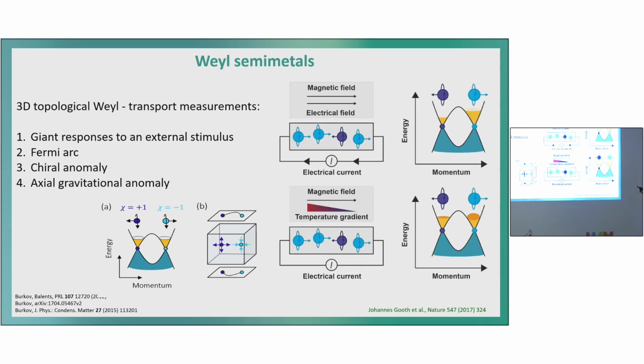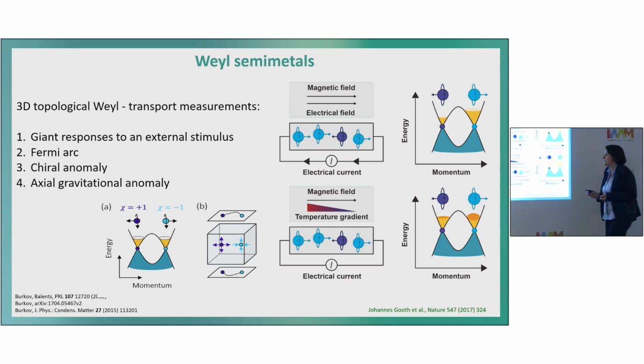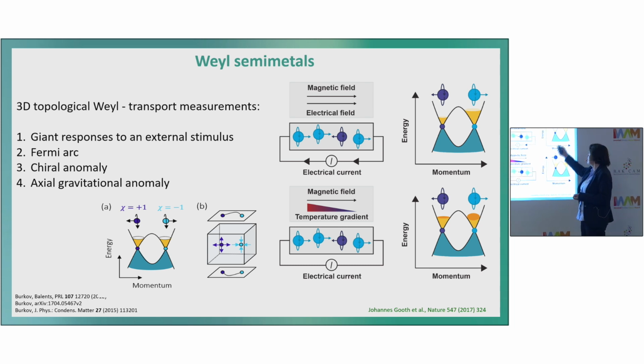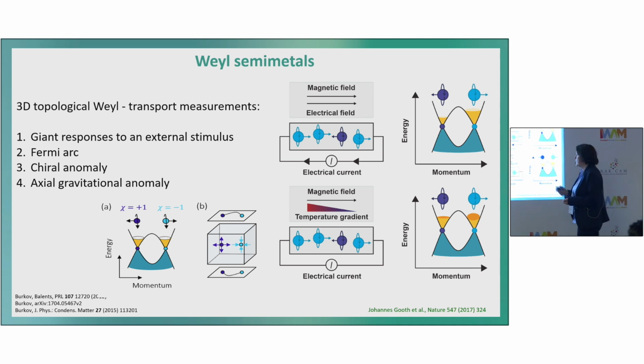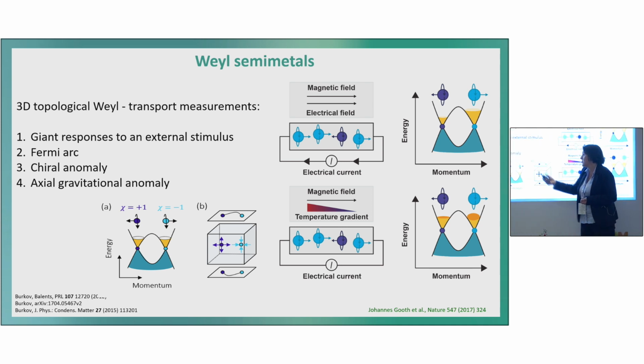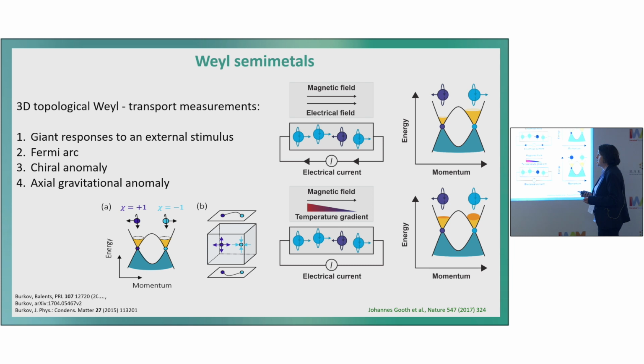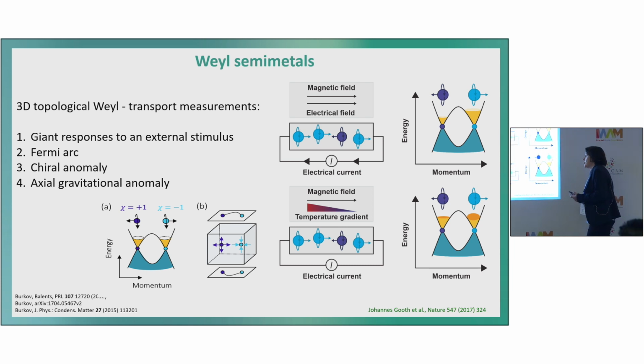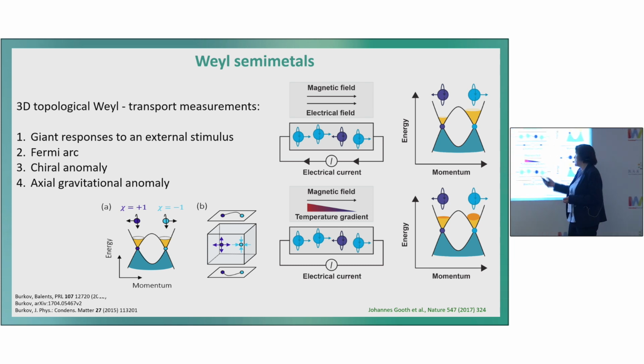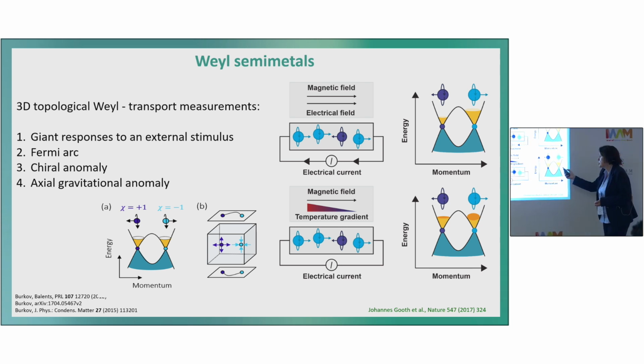If you apply a magnetic field and an electric field in parallel in the solid, you observe an asymmetry between electrons and holes in these Weyl semimetals. And there's even a further proposal, based on some work of Subir Sachdev, that you see this axial-gravitational anomaly if you apply on top a temperature gradient, again leading to an asymmetry between the electrons and holes in the Weyl semimetals.